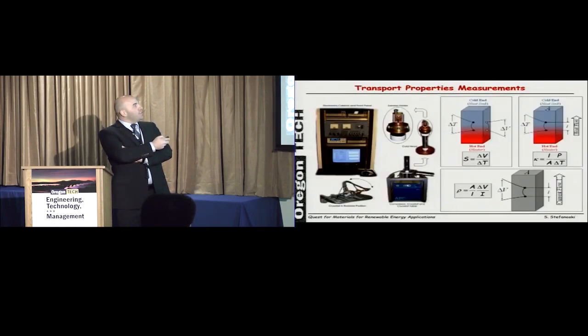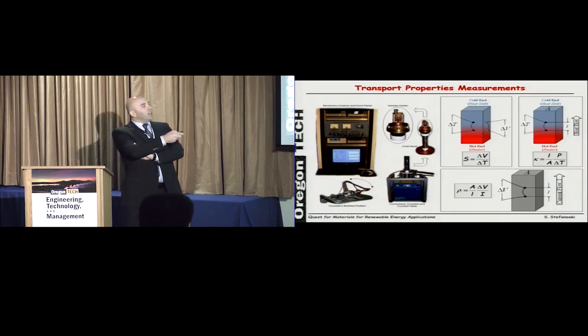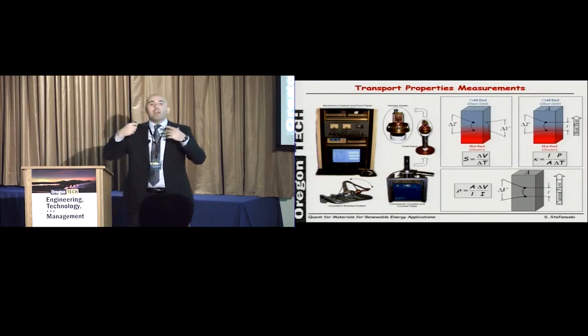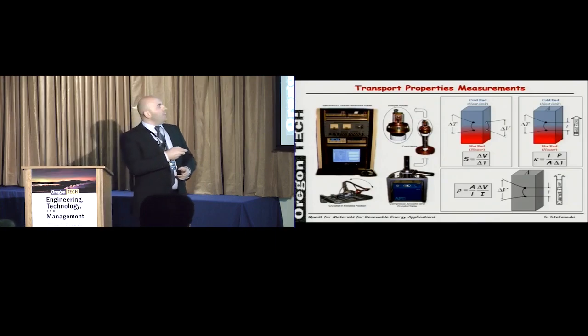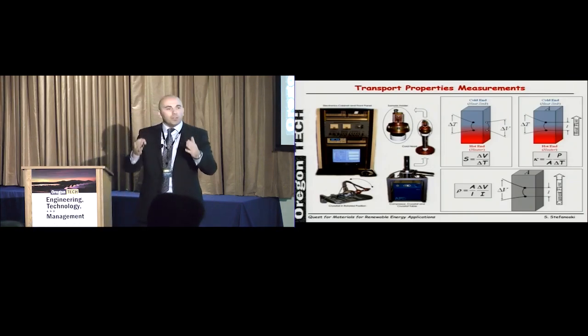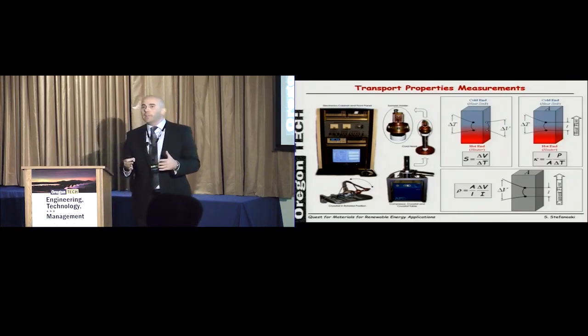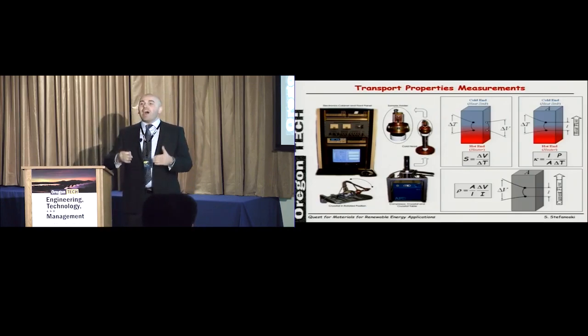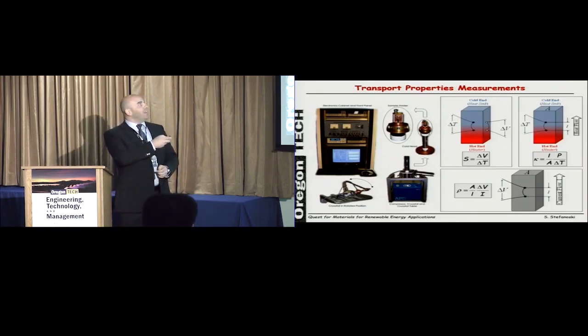In addition to synthesis, I just want to mention also that characterization of the materials is important, and measuring the physical properties. I'm not going to go into details here, just to mention that this is a transport property system that was designed to measure electrical conductivity, thermal conductivity, and Seebeck coefficient on materials, designed and assembled by students. A very sophisticated piece of equipment that can measure all of these properties. For example, the thermal conductivity by simply measuring the power through the sample and the temperature gradient measured by a thermocouple and so on and so forth.